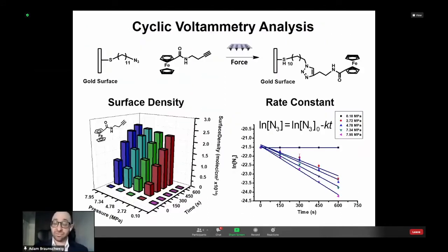So we went back and we repeated this with our redox active ink. And down here, you see the surface density as a function of both time and force. And this graph right here already explains a previous discrepancy in the literature. So what you see is that our reaction yields, or our surface density, increases with both time and force. And if you think of the work of both Stoddart and Reinhoudt, if you're not controlling for both factors, there's not going to be reproducibility between the groups, but since they couldn't control force, it's hard to compare the data. There's a third factor that also wasn't considered that I'll get back to.